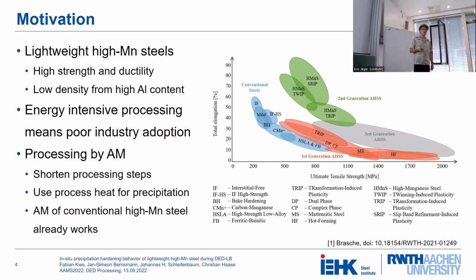And additionally, as I showed you on the last slide, it has like 8 weight% aluminium, which means that the density is reduced compared to other steels. However, this alloy is not really applied in industrial application because you need energy-intensive post-processing, mainly due to the strong segregation of manganese during casting, stuff like that.